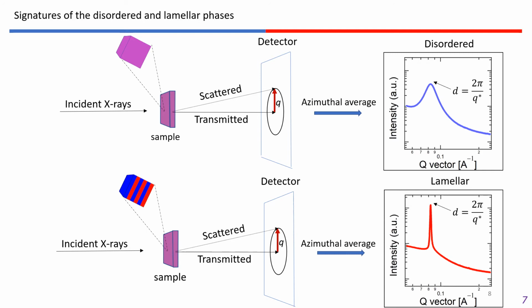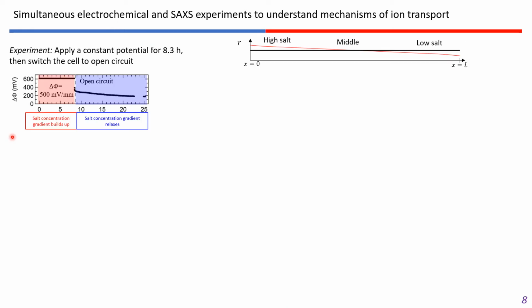Just to briefly go over the analysis of the small angle X-ray scattering patterns, we pass X-rays through our sample and convert the 2D scattering patterns into 1D scattering patterns. For a disordered morphology, we get a characteristic broad scattering peak, and for a lamellar or ordered morphology, we get a sharp scattering peak, where in both cases the position of the scattering peak is related to the domain spacing. We're now ready to talk about the results of this electrochemical experiment.